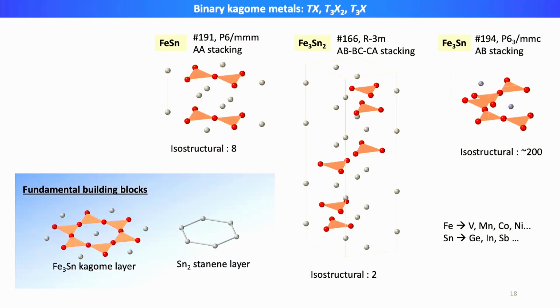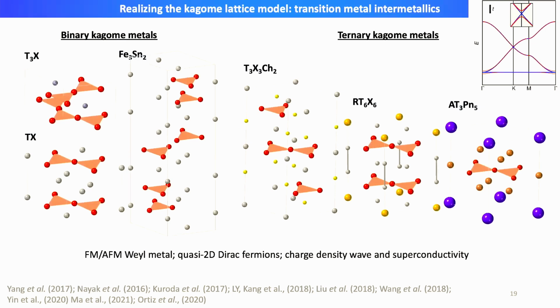So aside from these binary compounds, if we add a third element into the structure, we get a lot of structural flexibility. And here are three examples of ternary kagome compounds, where you can have these little sulfur atoms, or bigger rare earth and much larger alkali metals in between the kagome structures. But nevertheless, the common structural motif across the entire class of materials are these two-dimensional kagome layers within the ab plane that's highlighted by red here. So the reason I wanted to show you all these new varieties is to show you that this is really a large family of materials that are actively investigated in the field.